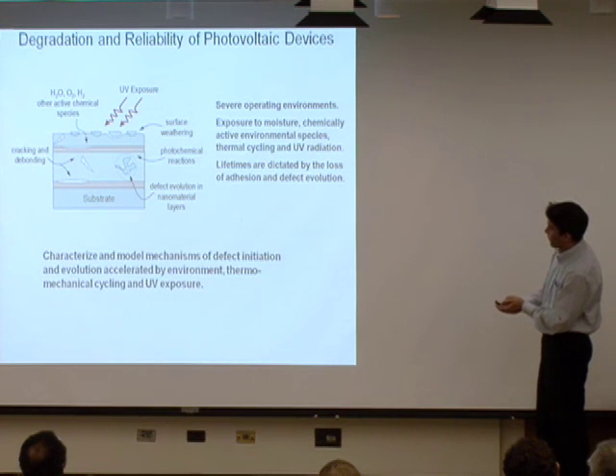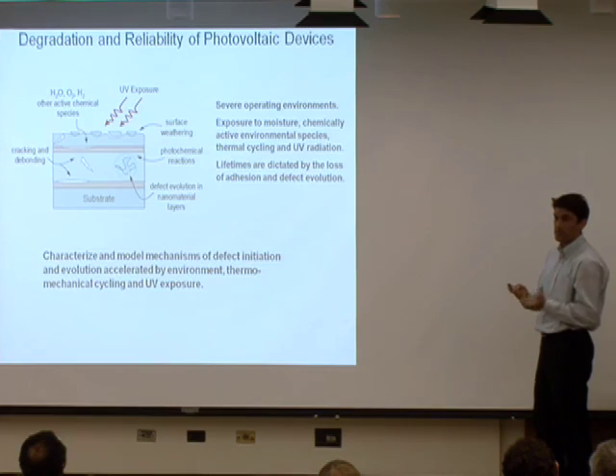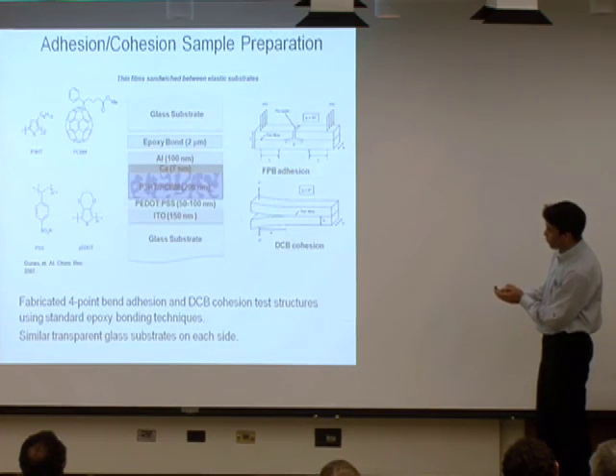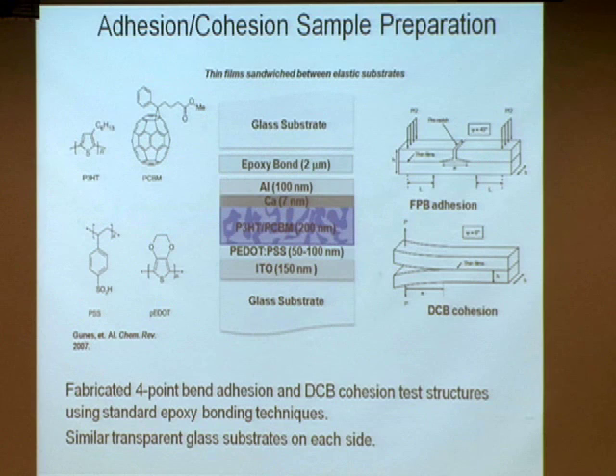But there's also this mechanical issue. So what happens when you flex this? Where is the failure occurring? And this is work done in Reinhold Dauskardt's group here at Stanford. So if you look at the cross-section of a typical device, there's ways that you can stress this device. So he is taking this and basically shearing it or physically trying to peel this away and then going back and looking at what happened as a failure mechanism.